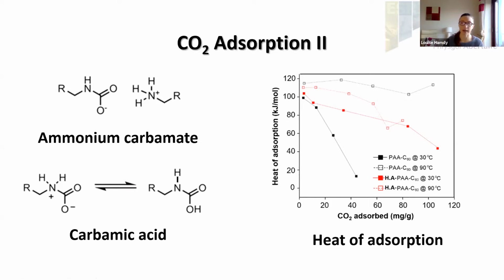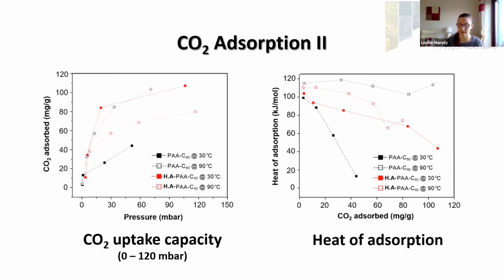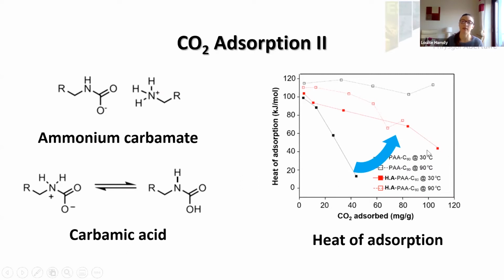So on inclusion of the hydrophobic additive, at 30 degrees, we see that the heat of adsorption is essentially increased. And this is due to the fact that the hydrophobic additive allows access to the amines to form the chemisorbed species, whereby at 30 degrees, the PAA-C60 material is not always chemisorbing, and a lot of the adsorption is due to physisorption interactions, which have a lower heat of adsorption.